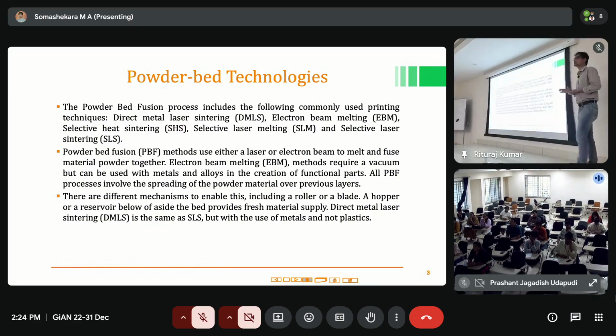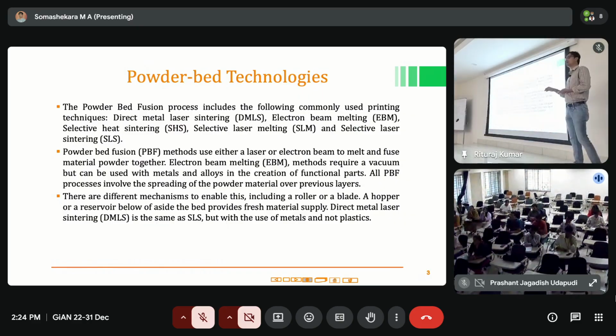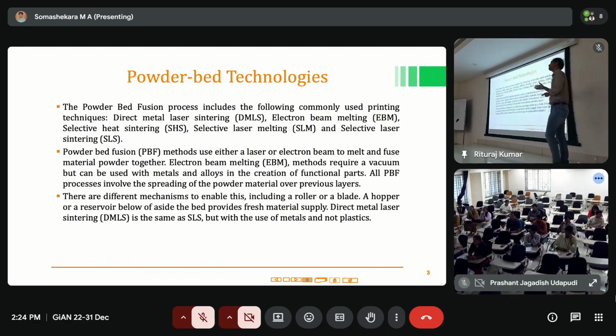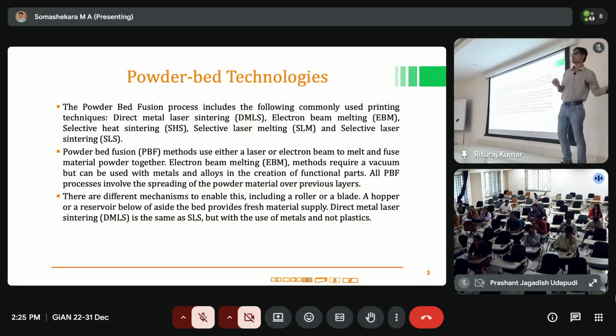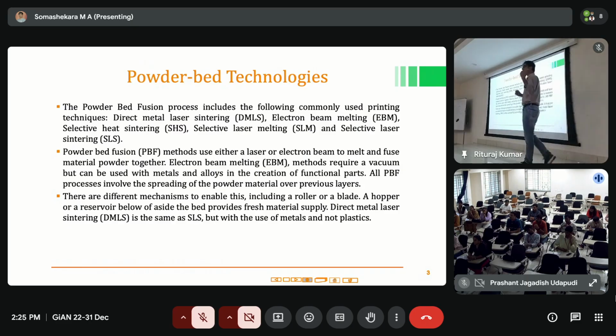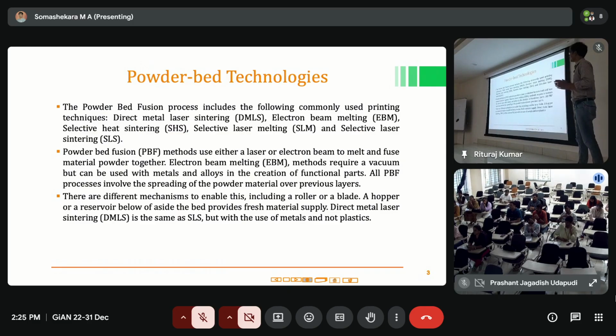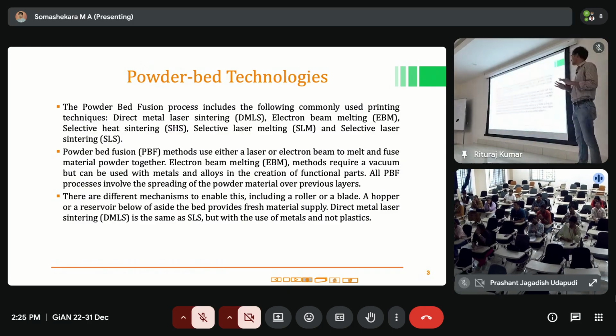That material will stay next to your fused material, which means there are three different zones in this case. One is the fully fused metal, then the partially fused metal, and then the material not melted at all. Wherever the laser fully comes in contact, you will see fused material, and wherever it is slightly in contact, a little bit away from the fused material, you will have partially sintered material, and the rest the laser will not come in contact with at all.